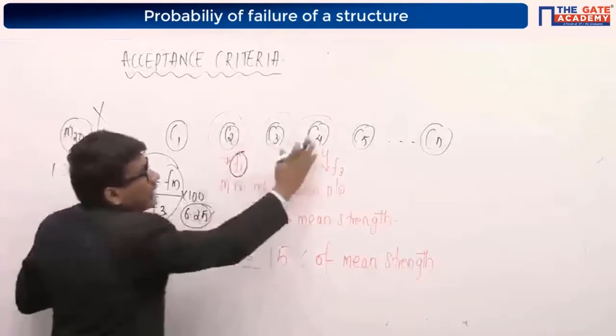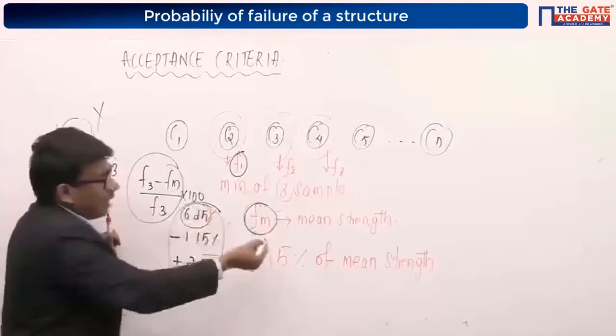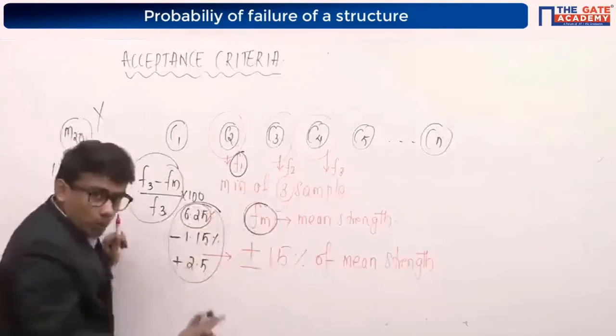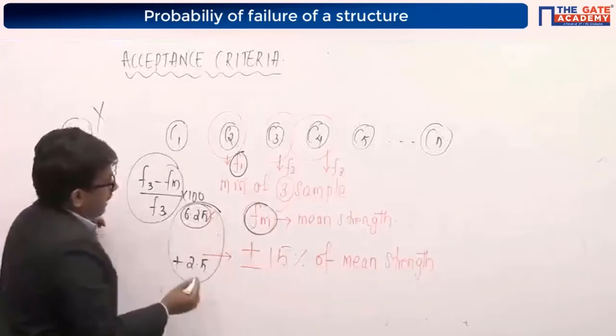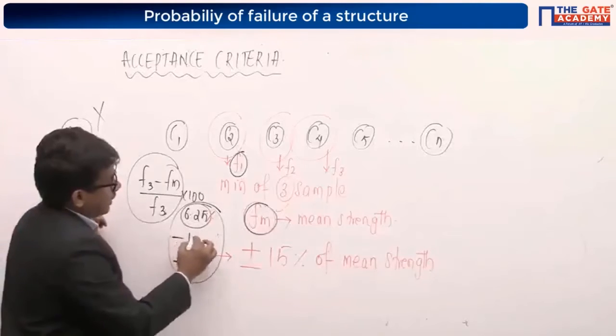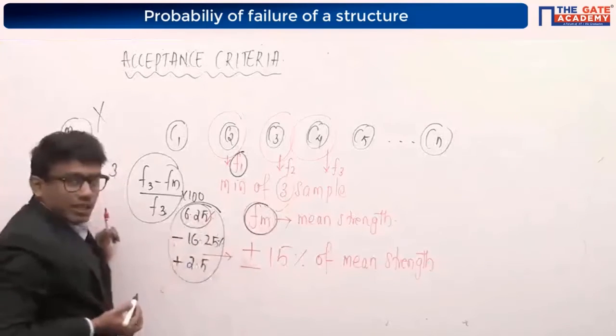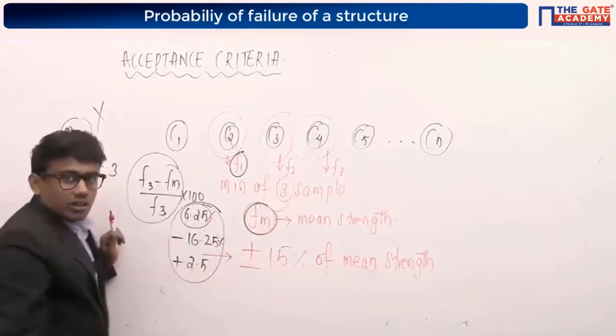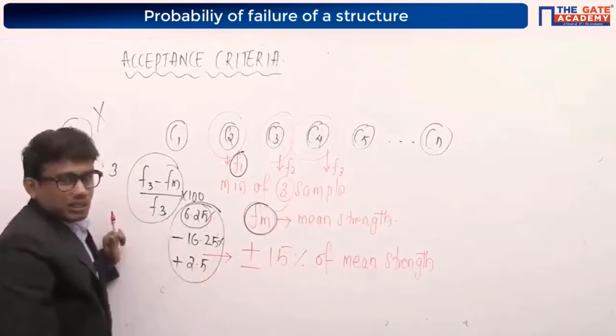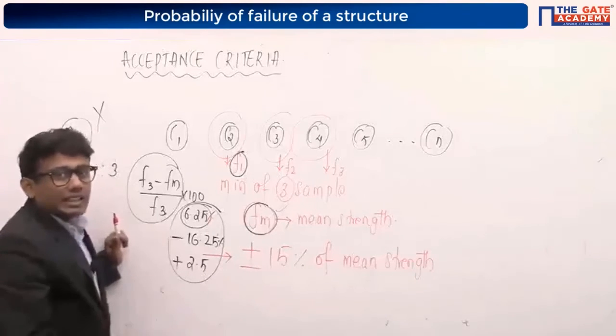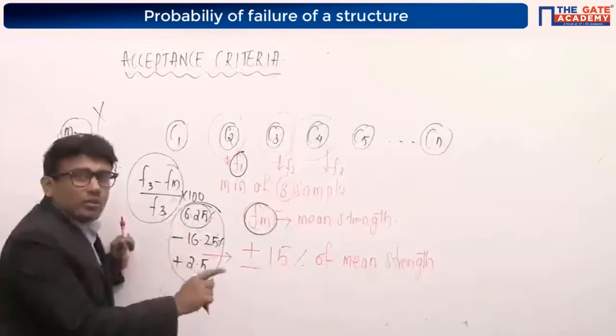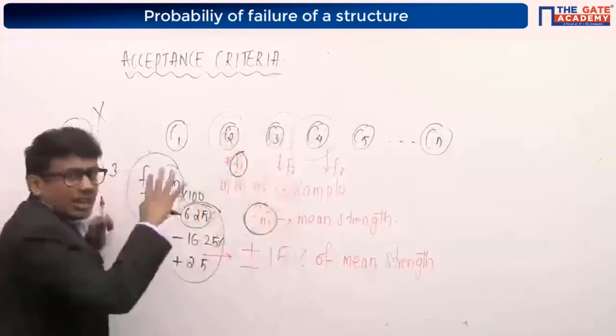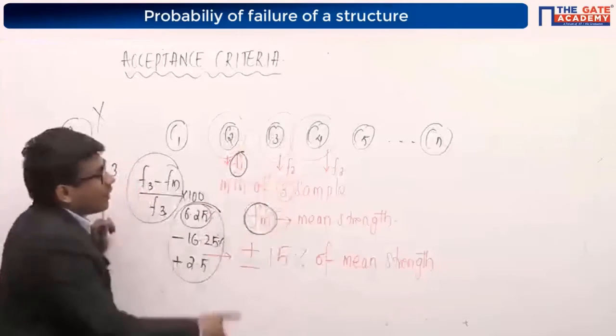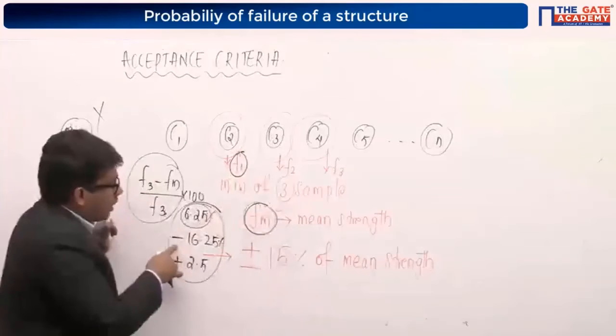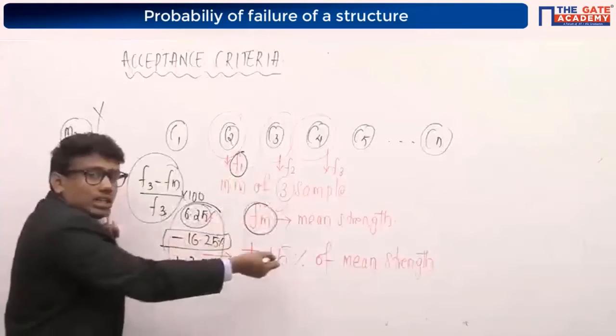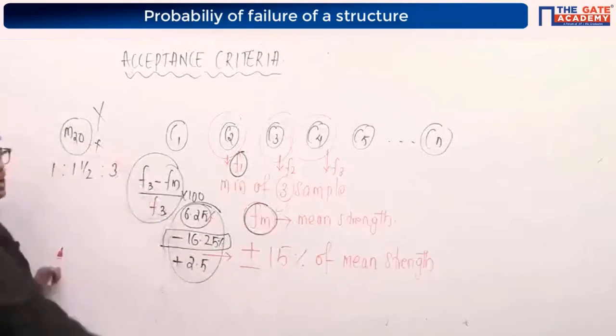Why? Because for all the 3 cubes, the percentage variation is within plus or minus 15%. Suppose instead I got around minus 16.25%. Tell me, will I accept this concrete or not? No, we cannot accept this. As per IS 456-2000, the code is saying that you should not accept this concrete. Why? Because you have taken a minimum of 3 random samples, and when you calculated the mean strength and the percentage variation in the strength, you obtained a variation which is more than this plus or minus 15%. So you cannot accept this concrete. That's the meaning of it.